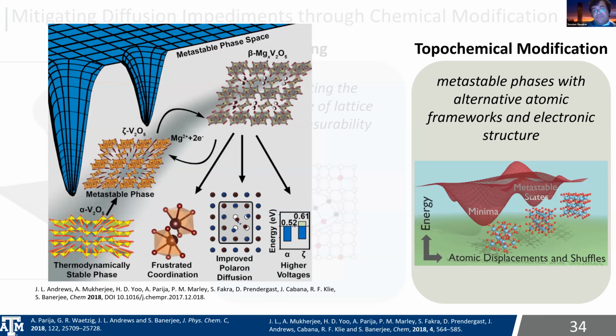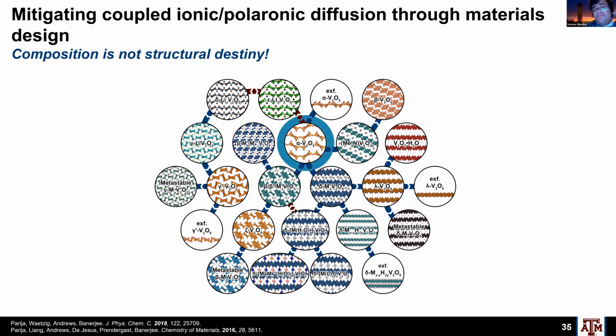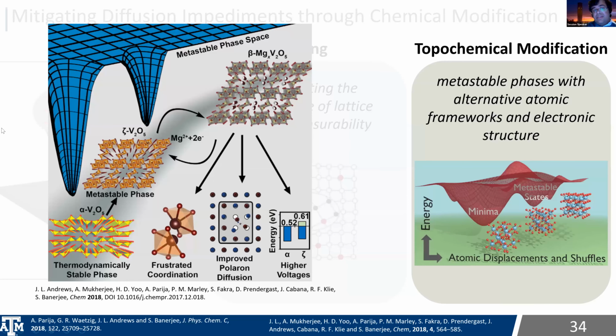So we've spent a lot of time identifying and stabilizing metastable V2O5 phases. We've conceptualized, in some form or other, more than 10 new metastable structures that allow us to essentially define entirely different diffusion pathways for ions based on rejigging the atomic connectivity in these structures. Okay, so the idea here is that composition is not structural destiny, that you can think about these as energy landscapes, where the thermodynamically stable phase could be the deepest well, but there exist local minima that are quite readily accessible.